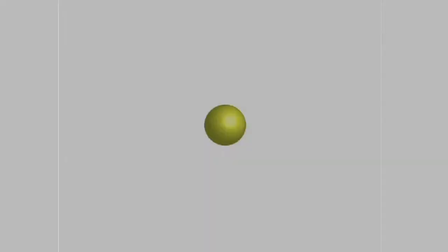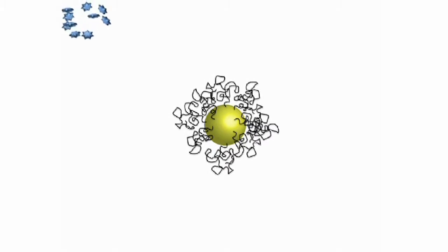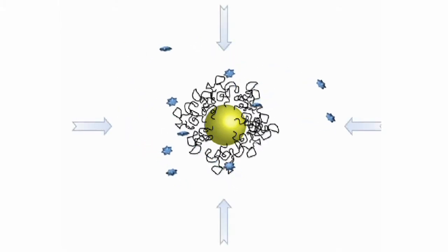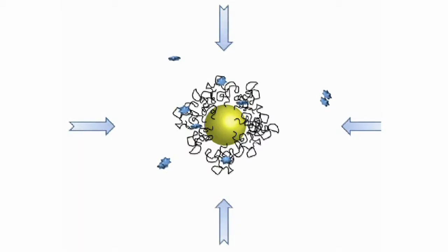Well, we've been working to understand how to improve the delivery of hydrophobic photodynamic therapy drugs in vivo using nanoparticles. And really, laser spectroscopy provides critical insights into how molecules interact with nanoparticles in solution. In our system, we have a gold nanoparticle, and it's coated with an amphiphilic ligand called polyethylene glycol. When you add drugs to the solution, the nanoparticle will actually stabilize it and keep the drug protected, especially in polar media such as water, where the drug usually aggregates.